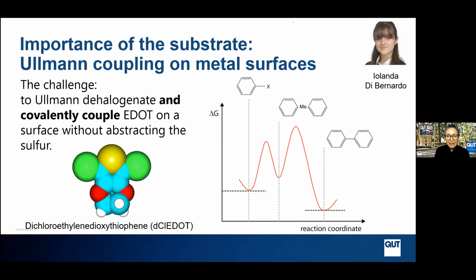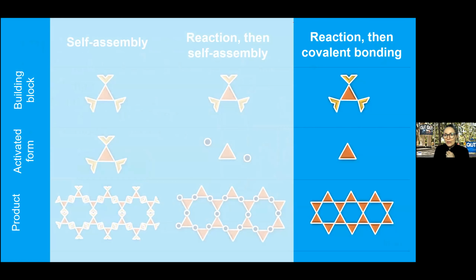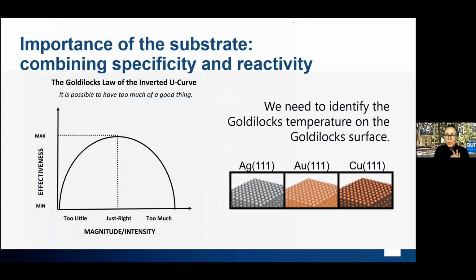The tricky bit is getting through that conversion of the organometallic to the covalent polymer. That's because there does tend to intrinsically be a pretty high barrier to that conversion. So we run the risk of either desorbing our molecular precursors, or, in the case of this very baroque molecule, of breaking it because it's full of heteroatoms. So here we're pursuing reaction, then covalent bonding, but the difficulty is we need to find a surface which is reactive enough to dechlorinate the molecule, but not break any of these carbon heteroatom bonds. So we need a surface which is reactive, but not too reactive, and we need to find the correct reaction temperature.